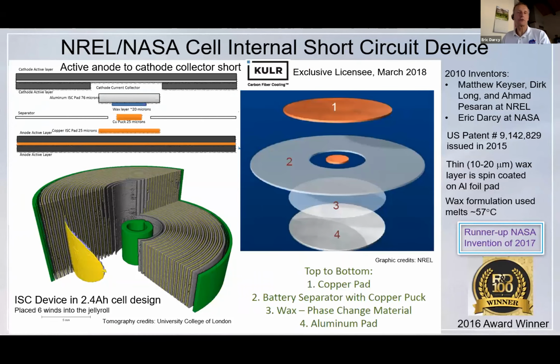And in order to trigger thermal runaway, we use the NASA NREL internal short circuit device, which is embedded inside the cells and has a wax layer that melts at 57 degrees and produces a hard short due to the winding tension that's in the jelly roll. This is what we think is the best way to represent a field failure of a hard internal short. It allows us to only have to heat the cell to over 57 degrees to produce a hard short that produces a thermal runaway response.